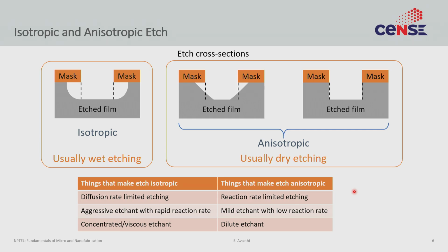So I urge you to remember the lectures on diffusion, where we had two cases, where the etchant solution, sorry, the deposition precursor was coming in, diffusing through a boundary layer, getting to the surface and doing a reaction. We talked about how these two fluxes, the diffusion flux and the reactant flux, have to be in balance, and that led to the two different regimes where the deposition reaction could either be diffusion limited or mass transport limited, or could be surface reaction limited.